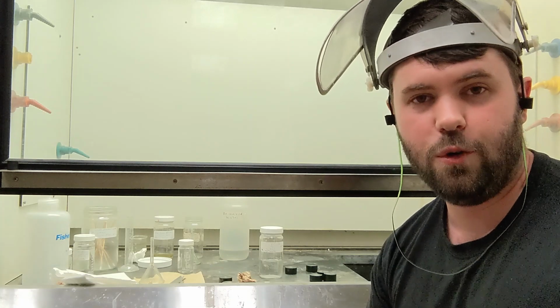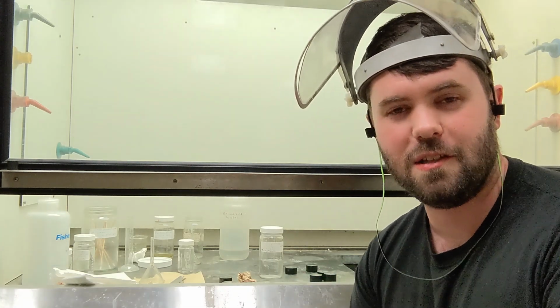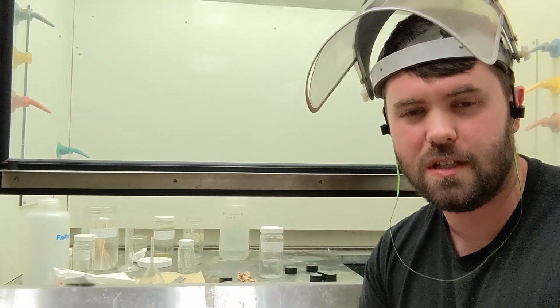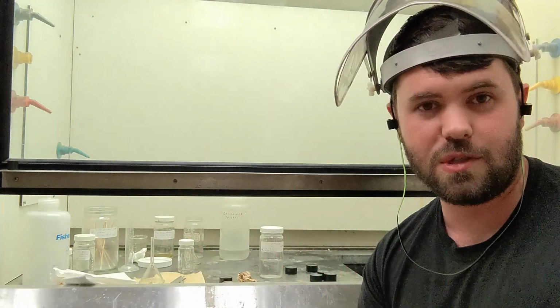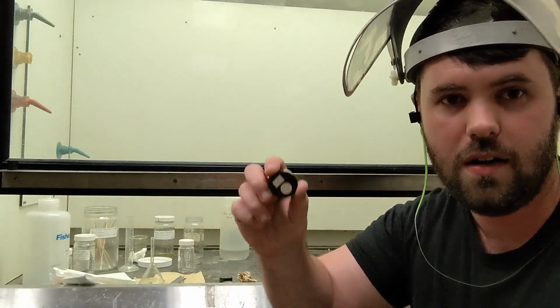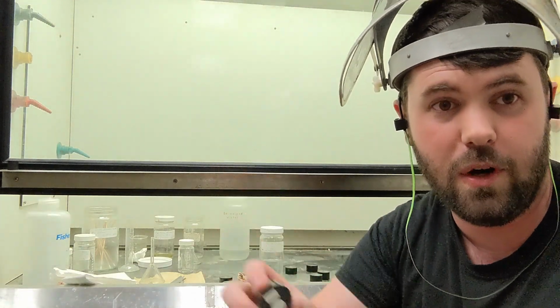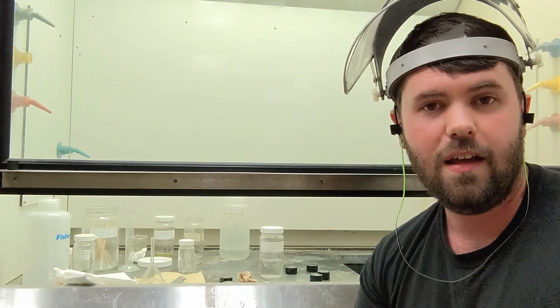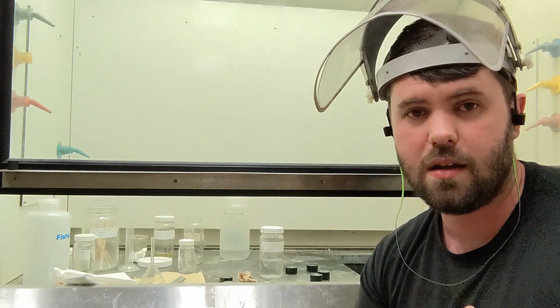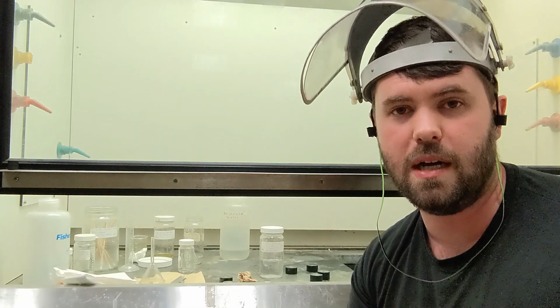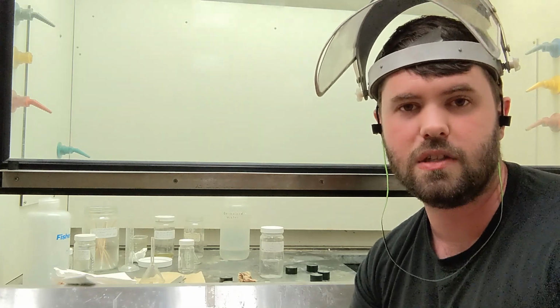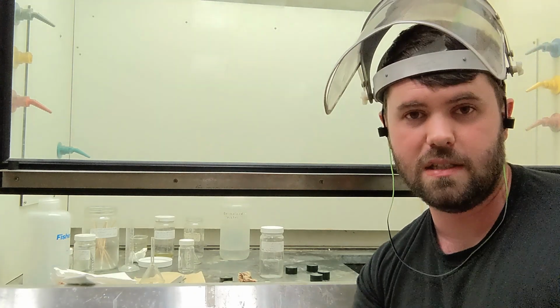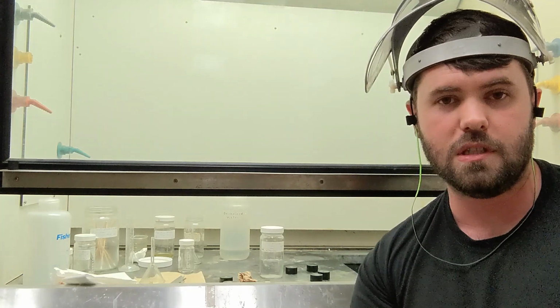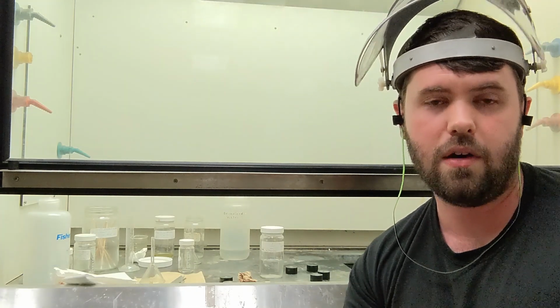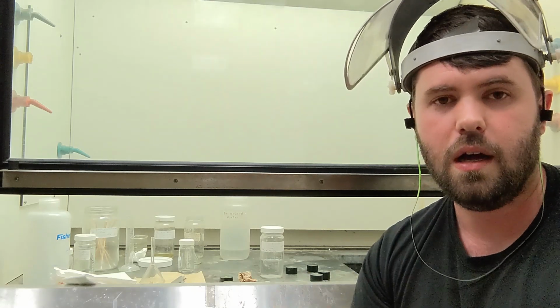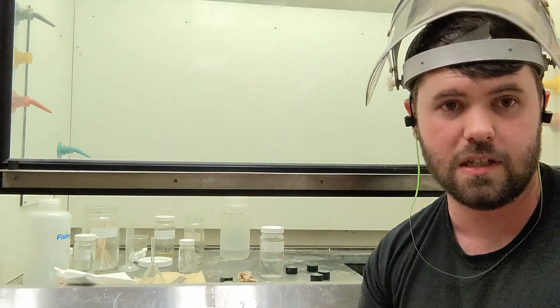So the final step before we do our microscopy to actually look at our microstructures, which this whole lab revolved around, we need to reveal our microstructure. So right now our samples are really nice and polished really well. They're mirror finish flat, but we can't actually see the microstructure, the things that make our sample special, the things like the grains, the grain boundaries, the different phases that we see. So in order to reveal these phases, things like ferrite, which is pure iron, or things like pearlite, which is iron and carbon layered on top of each other, we need to reveal them with etchant.